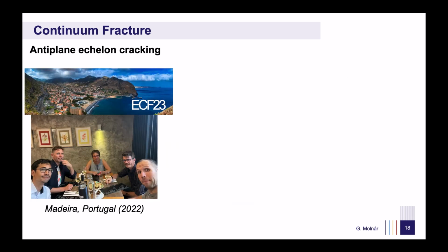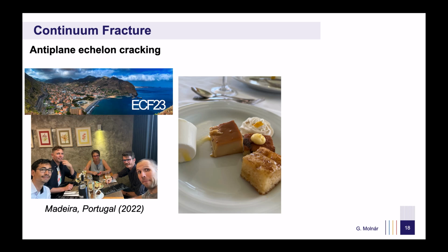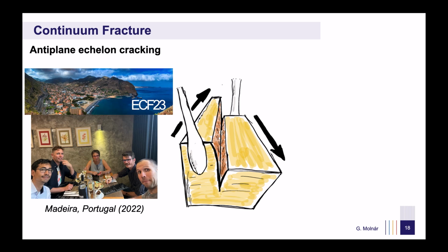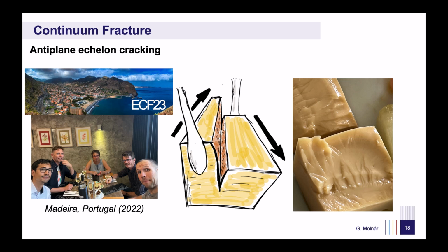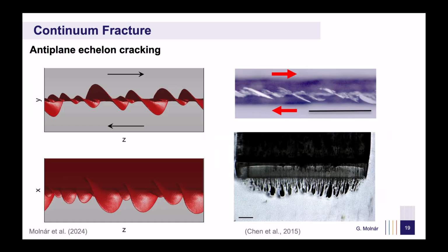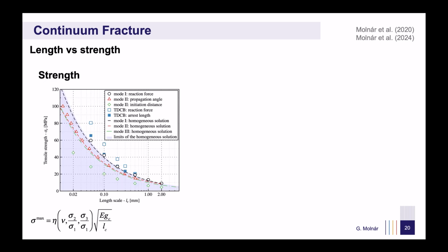The third example was inspired by the conference dinner in Madeira. During the dinner, my colleague Aurélien Doitrand sacrificed his flan, a gelatinous cube. He cut a notch in the middle of the dessert and applied anti-plane shear using 2 forks. Surprisingly, the fracture pattern mirrored those observed in many brittle materials, forming a hierarchical facet-like structure. Motivated by this, we applied the phase field model to solve the problem, and it successfully reproduced the facet formation seen in PMMA experiments.